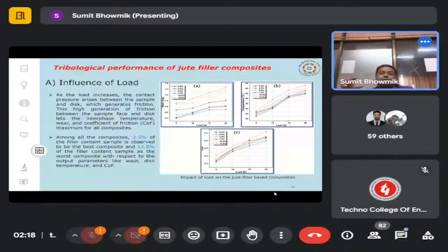Compared to other fillers, this has good properties compared to banana or pineapple or other components of the material. Now here if you see, when the load is varying, the wear rate increases with the increasing load, but the best property has been found at 2.5% of the filler for a jute composite. And as the load increases, the temperature also increases, and the coefficient of friction also increases.